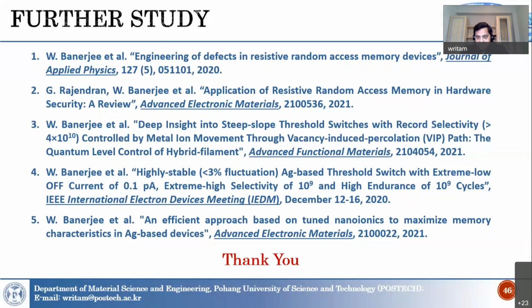It was not a silver-doped structure. It was a simple silver stack. So in that case, your top silver layer has to overcome a 200 nanometer gap, right? Yes. So you apply the voltage, and it takes about 1.5 volt to diffuse there. What was your initial forming voltage? Sir, initially it was forming at 1.39 volt. So almost 1.5 roughly, device to device. Yes, sir.